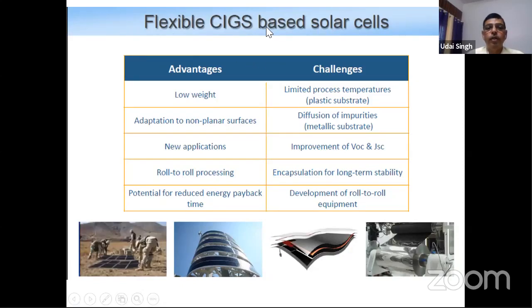The advantages of these flexibles are low weight, adaptation to non-planar surfaces, new applications, and roll-to-roll processing is also possible, because if you use a glass substrate, roll-to-roll processing is not possible. Also there is potential for reduced energy payback time. Energy payback time is how much energy you have used to create the solar cell and within how many years or months you can recover that much energy. Silicon has a longer energy payback time than copper indium gallium diselenide.